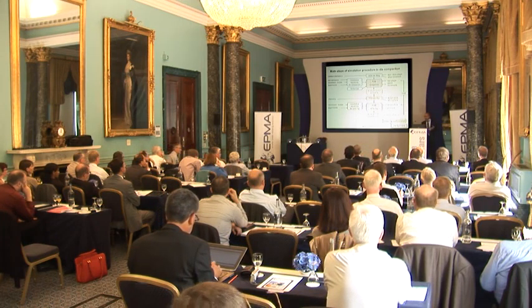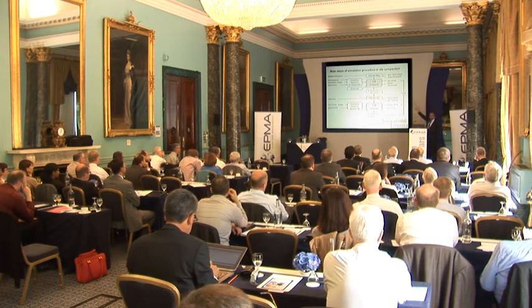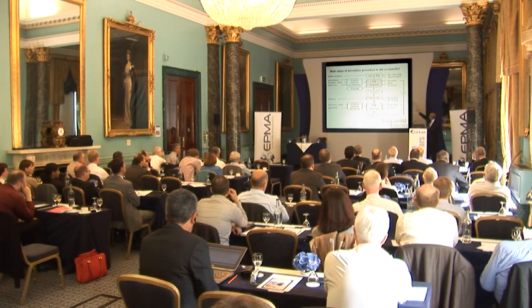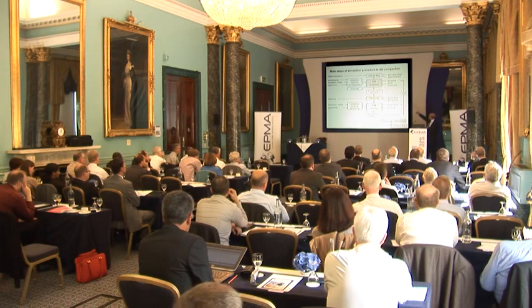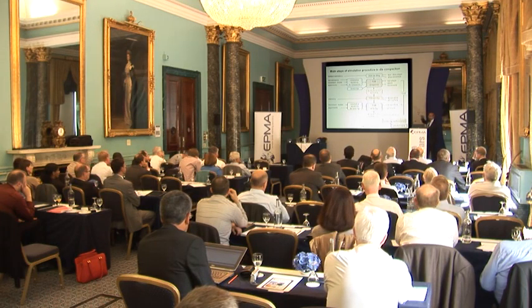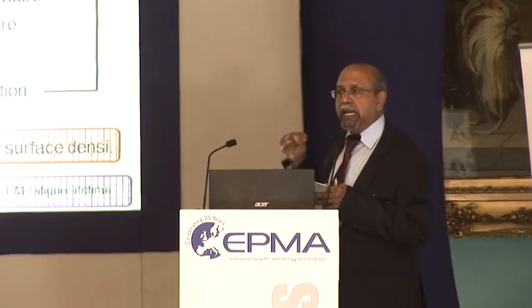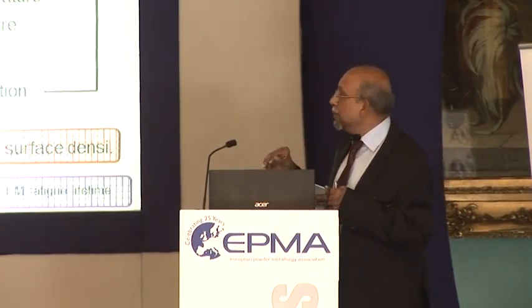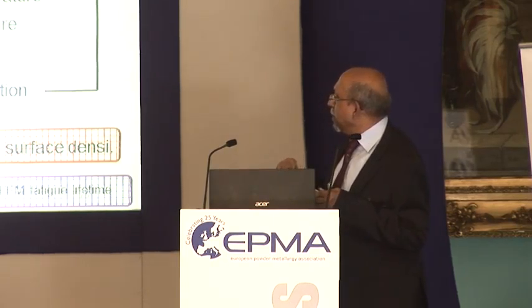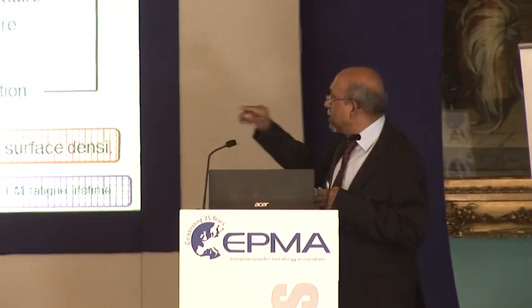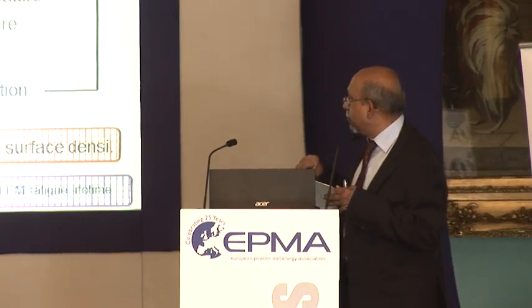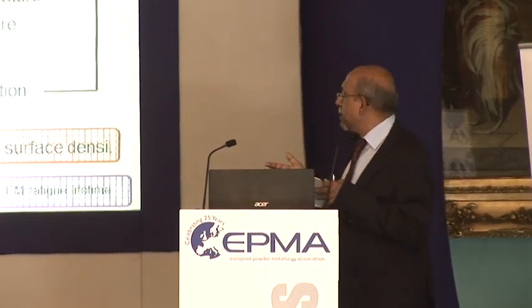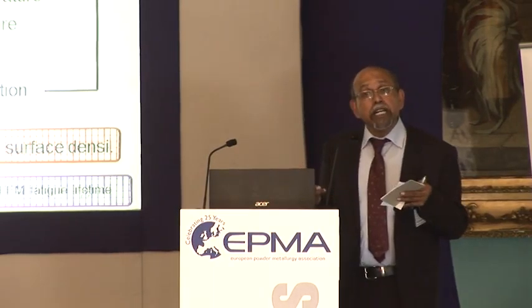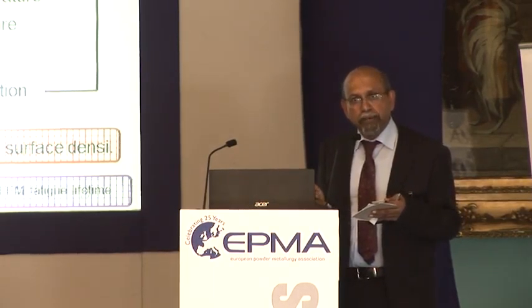And the main thing is, for example, this is an example for die filling. We have modeled the die filling, Peter, remember? Yeah, and FEM for compaction, density distribution, and tool loading. The new things are FEM calculations about debinding and about sintering, which leads to the fact that we have less sinter distortion and crack formation. So we can optimize the whole process and we get near net shape products by pressing.